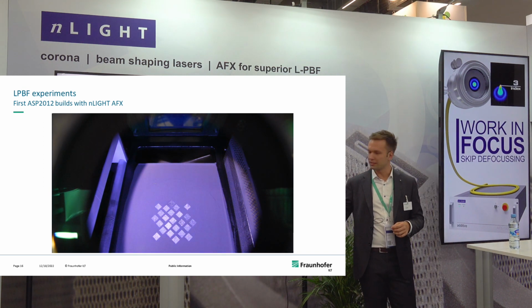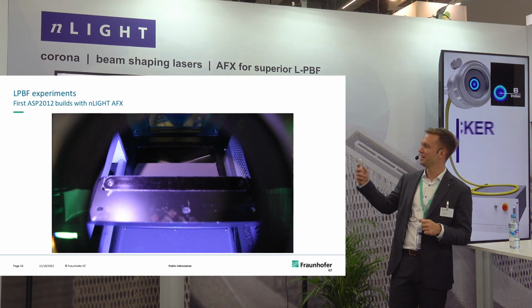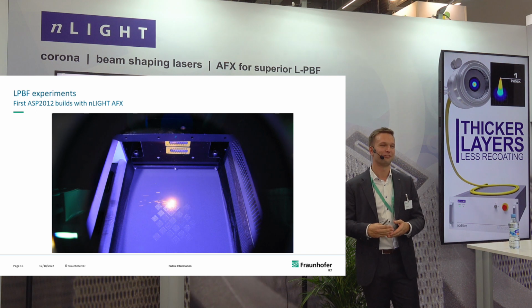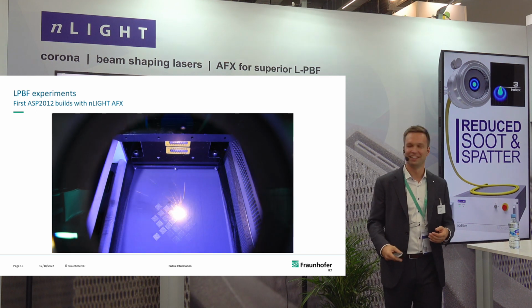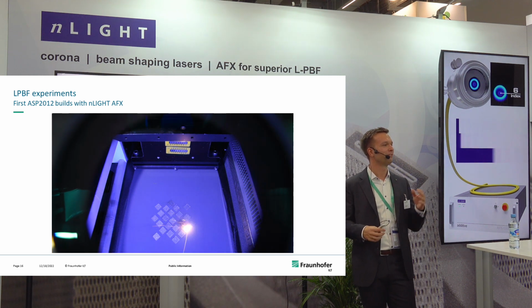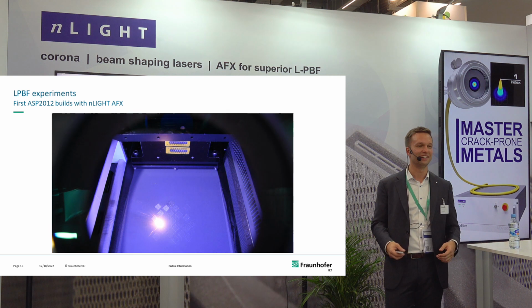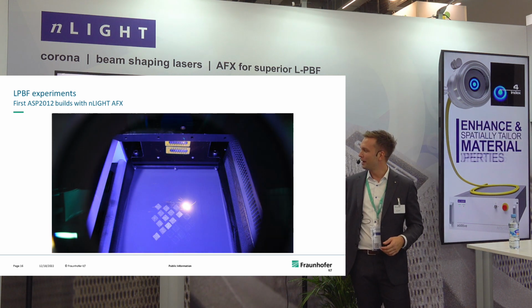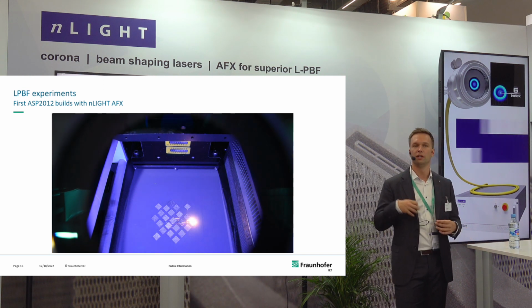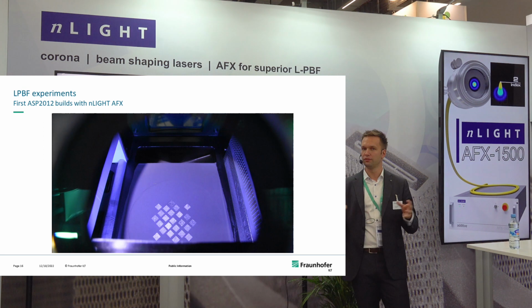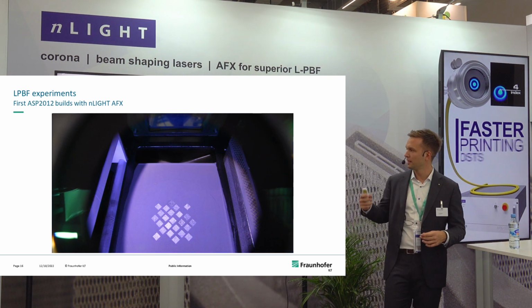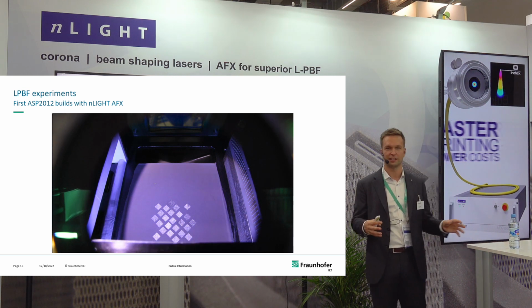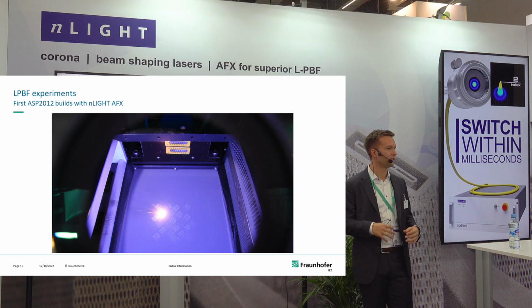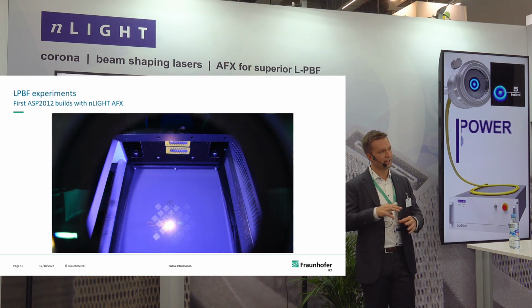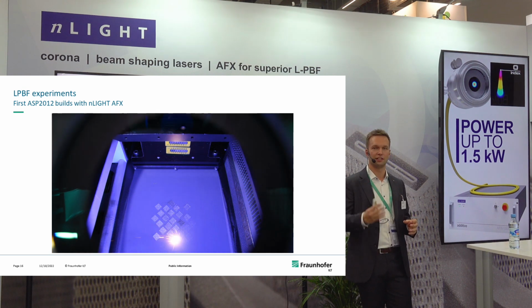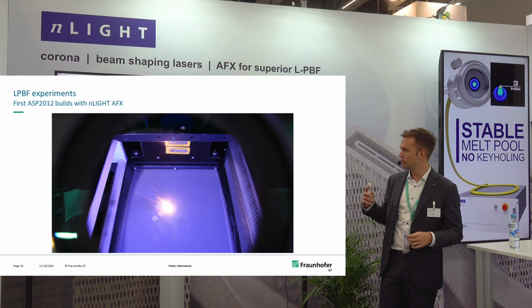I haven't got the results of the crack density yet, because you can imagine the material is very hard, so cutting the material from the plate and doing the cut sections for the analysis is quite challenging. You have to find suitable tools to even be able to cut the material, because this is usually used to cut other stuff. But first impression is the process works fine. We will do detailed analysis of melt pool geometry versus crack formation, and we really see a lot of potential in the additional degrees of freedom the AFX technology brings when it comes to processing of these hard-to-weld materials that are very sensitive to the temperature fields and the continuous remelting that usually occurs in L-PBF.